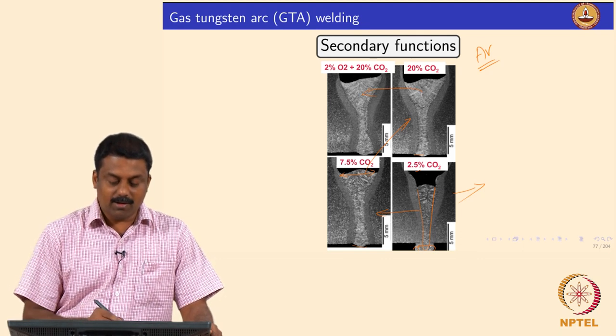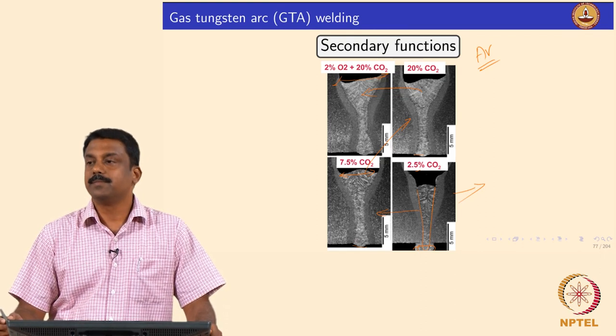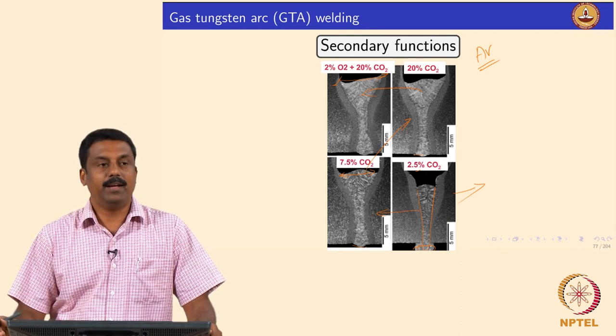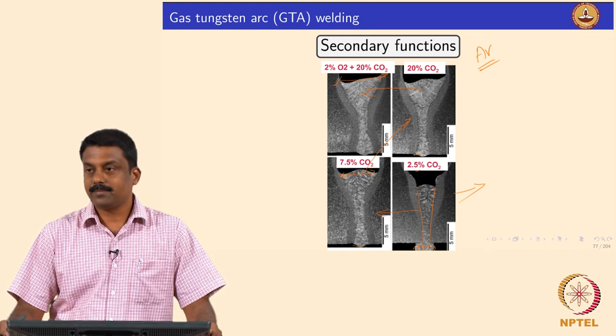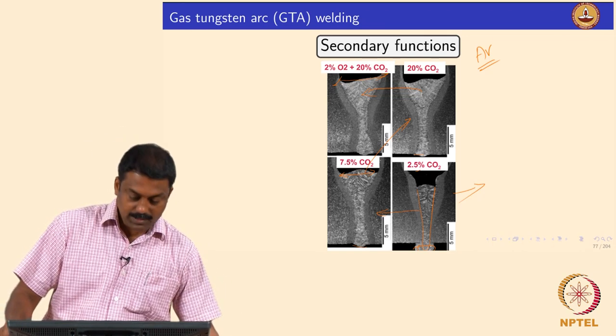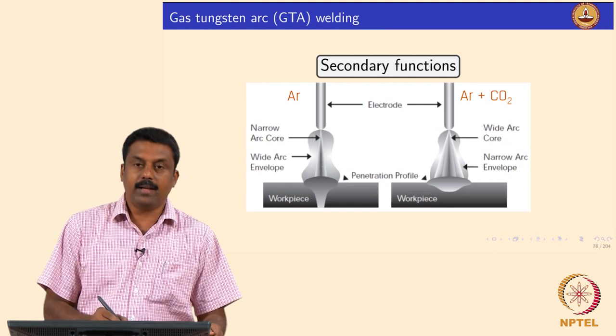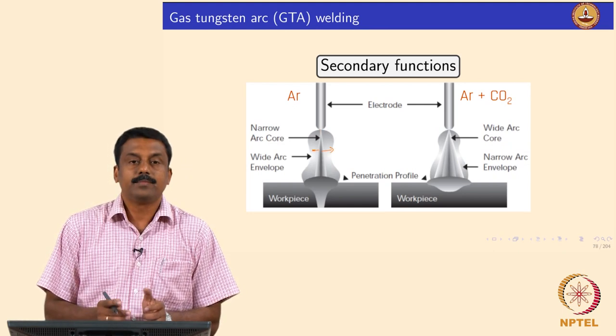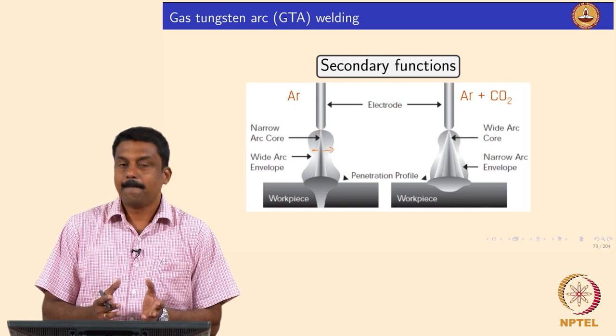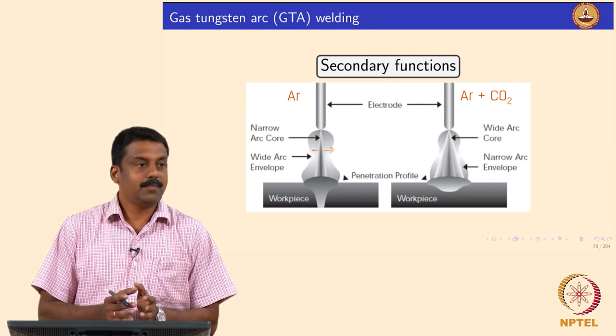From here onwards we added oxygen O2 — it increases the weld bead width further and the penetration decreases even more. This is due to the phenomenon already explained: the change in the heat transfer of the arc. In the argon case the arc core is very narrow because heat is not transferred; there is no convective heat transfer and no conductive heat transfer by de-dissociation, so heat concentrates at the core, leading to deeper penetration.